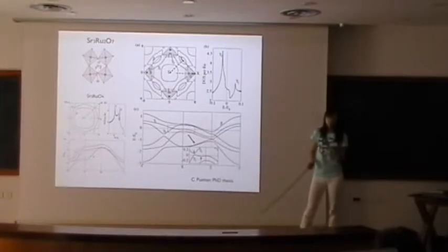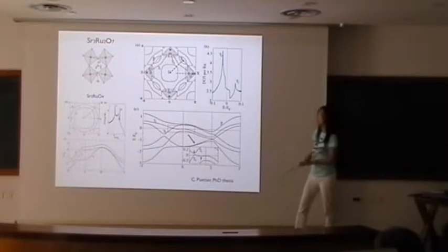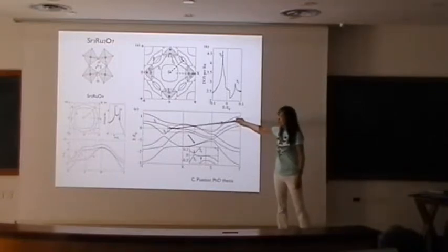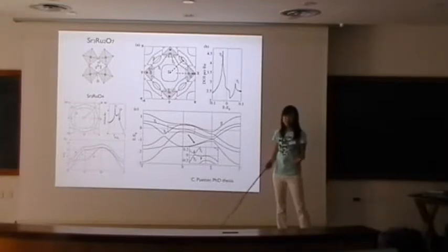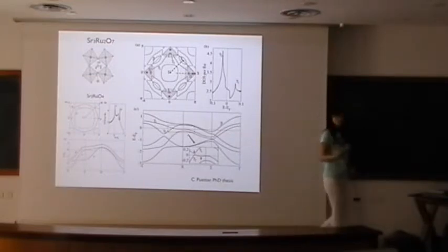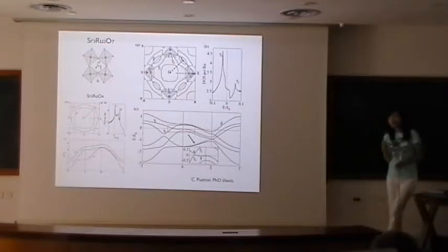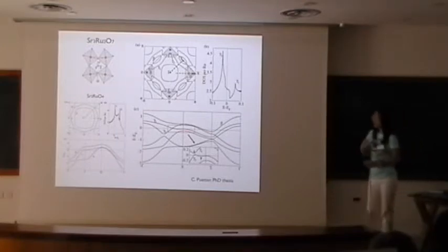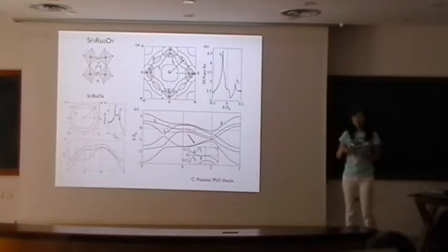But even if they don't meet, if the spin-orbit coupling is big, it tends to flatten the band, because atomic spin-orbit coupling is a local interaction, S_i dot L_i. Because of that, it tends to flatten the band, and a lot of people use it as a correlation effect. But they have to know that the spin-orbit coupling can also make the band mass heavy. So one has to always be careful, saying, oh, I got a flat band, mass is big, it has to be correlation. That's not the case when you have spin-orbit coupling, even if the bands don't meet.